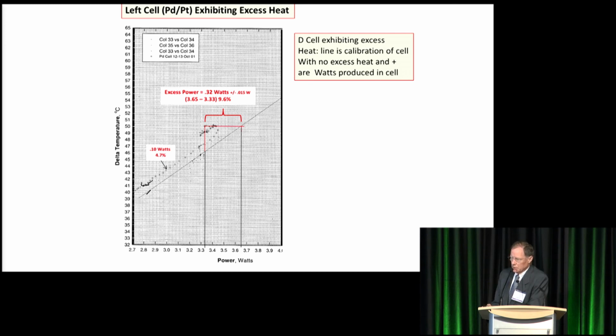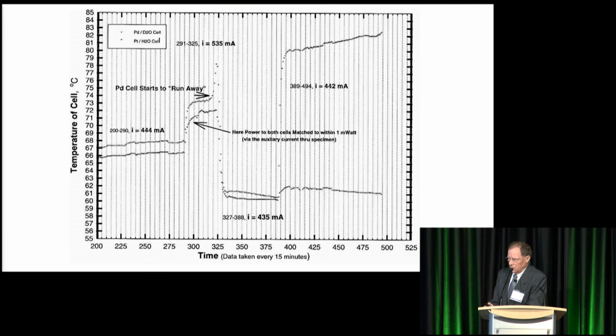So that excess power did change during the 46 days that it was produced, and some with only 1/10 of a watt is shown here. This is a particular series of interesting events where the lower is the light water cell, which has all the same time constants, everything identical to the heavy water cell, so that we're getting excess heat at 440 milliamps of current density. And then it was, at this point, increased the total current to 535 milliamps. And the heavy water started into a runaway mode, and I panicked, and I turned the electrolytic current down to a little lower than what I had before, and the excess heat came down.